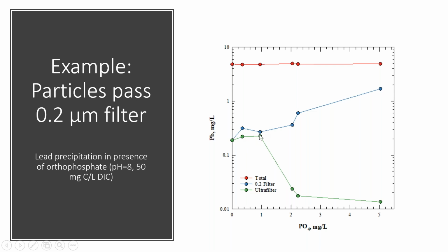So you don't really start to get a handle on what's going on until you get to a concentration where you have excess orthophosphate above and beyond what's needed to precipitate out the solids. In other words, you have soluble phosphate coming through the filter, and that doesn't happen until your total phosphorus dose or phosphate dose is above 2 milligrams per liter. I hope that makes sense.